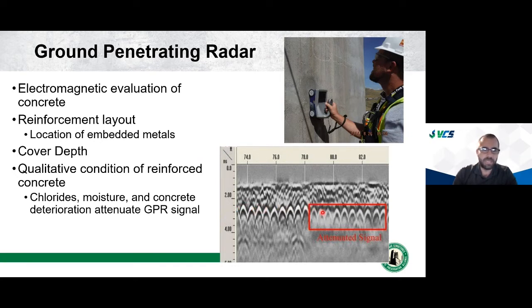And so we can see what the spacing of the rebar is. We can know what the cover depth of that rebar is. So it's really a useful tool if there are no as-built plans for a structure, for understanding where the reinforcement is. But we can also do a qualitative condition assessment of the structure. So you see here, this rebar on the left is very bright white, a really strong reflection. But the rebar over here is a weakened signal, an attenuated signal.